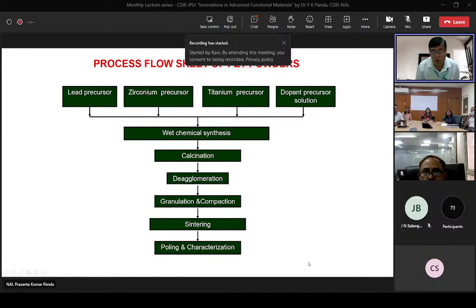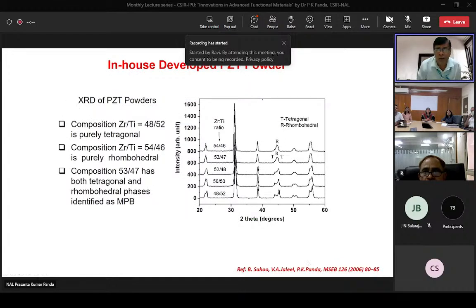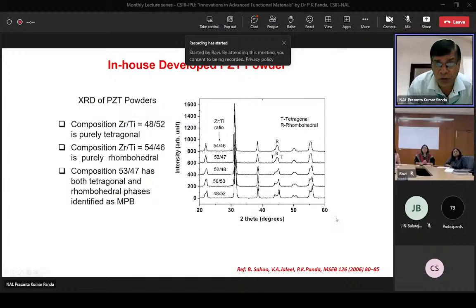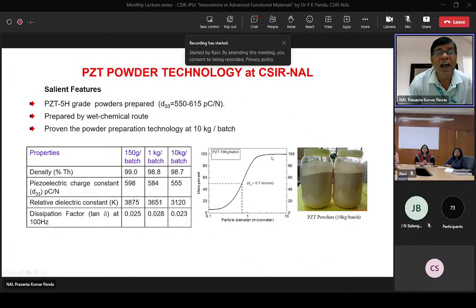This is the method for piezoelectric materials, and one should not forget to try different compositions near the morphotropic phase boundary to find the existence of both tetragonal and rhombohedral phases, to make sure that is the right kind of material you select to get the maximum piezoelectric properties. And after that, dopant has to be added.